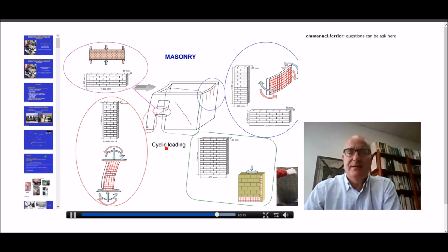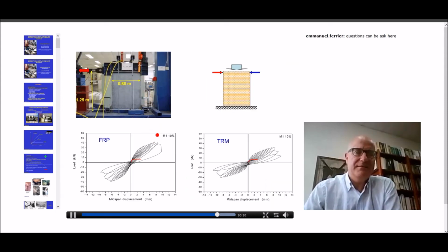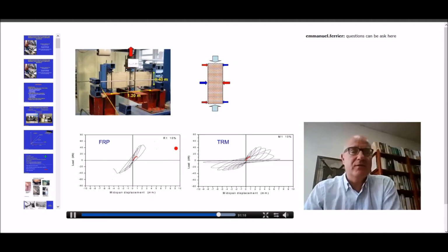Those bidirectional textiles are quite more effective than the FRP fabrics. One can prove that by doing simple tests. I will only show you some typical results. For example, if you have a masonry shear wall subjected to in-plane shear, the response of this member in the absence of strengthening would be what is illustrated by the red curve. If you retrofit it using a single layer of an FRP, that is of an epoxy-based jacket, you would get what is illustrated in black here. If you do a TRM, a textile-based jacket, you get what is illustrated in black to the right. By comparing the two, you see that TRM is nearly as effective as FRP, and we get a much higher increase in capacity in comparison with a control specimen.